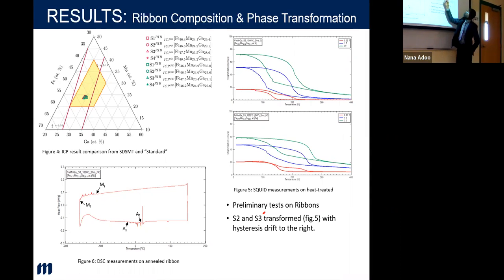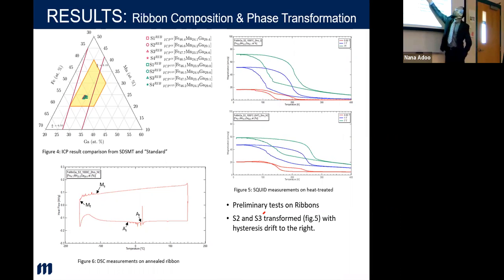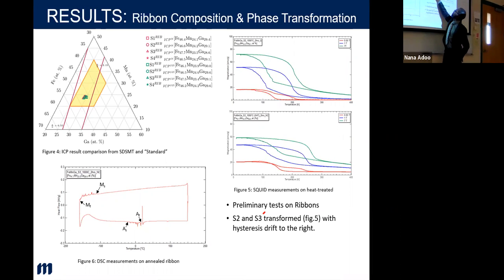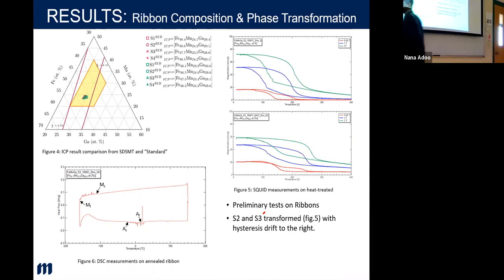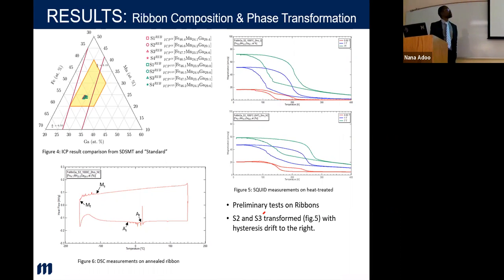this is a heating and this is a cooling. So you cannot go this way, and then in a kink here, you could see the starting temperature here, which is in the heating zone, where these tangents actually meet is one of these temperatures, which is the austenite. And then when you're cooling, it starts here. Let's use the green then. The bend here and then the intersect relates to this cooling here, which is starting here, and then here is the finish of this thing here, which is also related to this particular temperature. And so the range between this and this is the martensitic transformation, and the heating becomes the austenite transformation range.